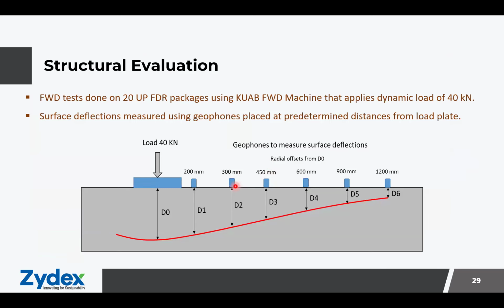Further, now I'll be showing a few of the results from the FWD test that we have done on the full depth reclamation packages in UP. We have evaluated almost 20 roads using the KUAB FWD machine, which applies a standard dynamic load of 40 kilonewton on a bearing plate. We have geophones at standard offsets of 200, 300, 450, 600, 900, and 1200 mm, and then we measure the deflections at these locations and find out the deflection bowl.